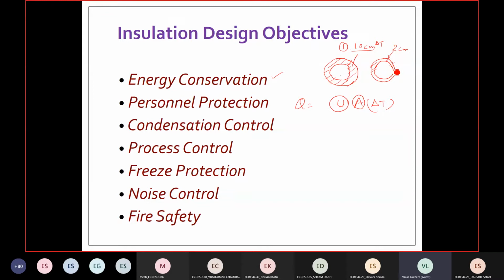as compared to this area. So even though the outside wall temperatures of the two surfaces are the same, for the pipe, this material, say type 2, requiring only 2 centimeter, is able to create the same thermal resistance as 10 centimeter because of its very low thermal conductivity. As compared to this, the wall thermal conductivity is higher, though it is an insulation. So the smaller thickness of this wall will lead to a lower value of Q. Even though both walls are at the same temperature, Ts, the area here will be lower, so you will have lower heat transfer to the atmosphere.